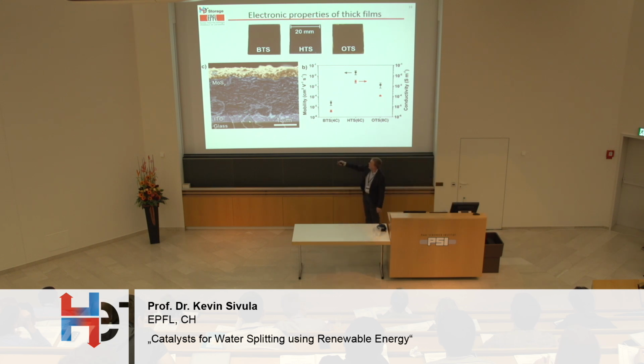And while these films are quite thick, we can put a top electrode on them and measure the charge transport through them, but I can tell you that the conductivity or the charge mobility that we measured is actually quite poor, probably because we have to hop between all of these different sheets to get all the way up to the electrode. But more importantly, we see a trade-off between the length of the carbon chain here and the electronic properties. So in this case, the BTS, which is a very short chain, we found actually performed the worst as far as the electronic properties, and this is probably because the shorter chain doesn't disperse the flakes as much, and I don't show it here, but we have larger aggregates and void spaces in that sample.